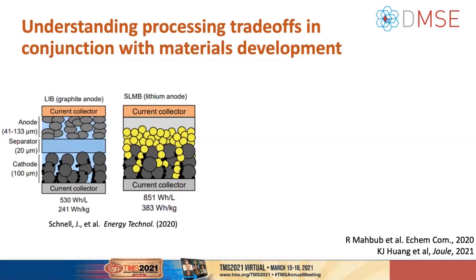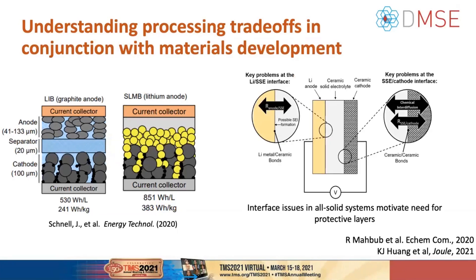Now thinking about more forward-facing technology, we consider processing trade-offs in conjunction with materials development — in particular for solid-state electrolytes. By enabling the use of thin, high-capacity metal anodes and electrolyte separators, we could potentially have solid-state batteries for higher energy density performance. However, successful integration of solid-state electrolytes into fully all-solid-state batteries remains a largely unsolved problem, particularly due to interface challenges on both the anode and cathode sides, where processing costs would introduce chemical interdiffusion or development of a solid electrolyte interface layer leading to higher resistance.